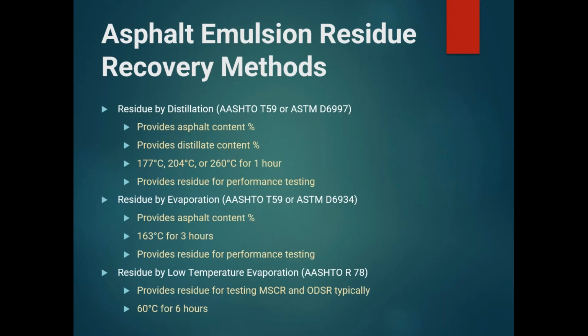And this residue recovery method will also provide you with an asphalt content percent, how much distillate content is in the emulsion, and also provides you then residue for performance testing. The second method is residue by evaporation. This is where the emulsion is poured into metal cans or containers and put into a 163 C oven for 3 hours. This provides you just asphalt content. You will not get a distillate percentage from this test. And it also provides quite a bit of residue for performance testing.